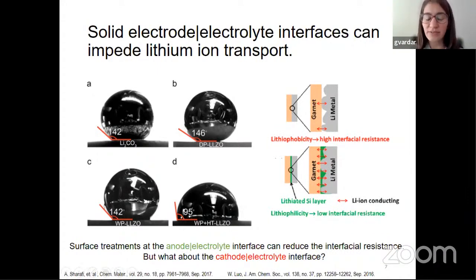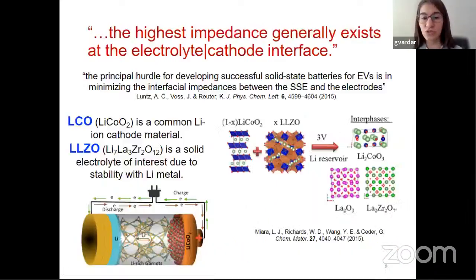However, the problem that we are currently facing to have a high power density solid electrolyte, which will be extremely safe, is the impedance between these two materials, this lithium cobalt oxide, and let's say this solid network, which we take as LLZO. This is one of the most promising solid electrolytes, and this is a very common cathode material. The thing is, this interface is the thing that's keeping these solid batteries from being highly commercialized. It's because there is a high impedance. Impedance meaning the lithium cannot cross over through the interface.